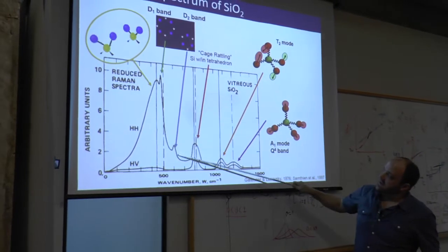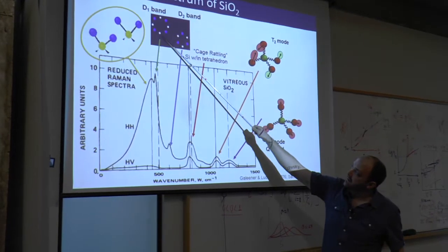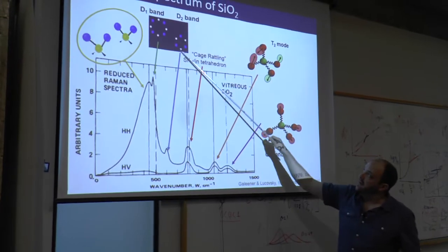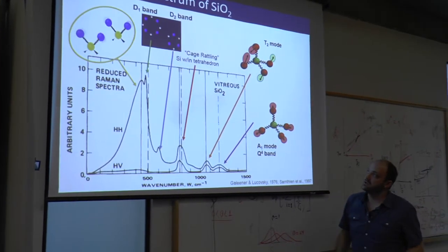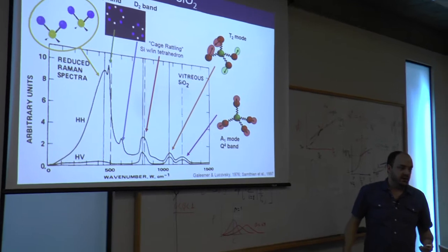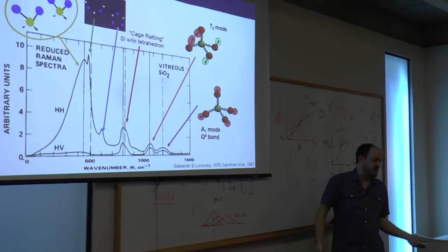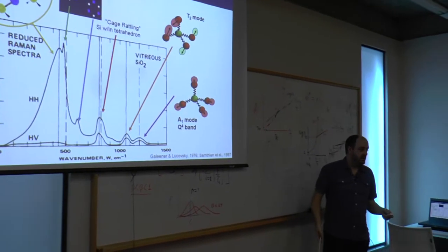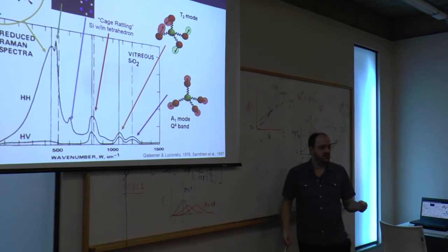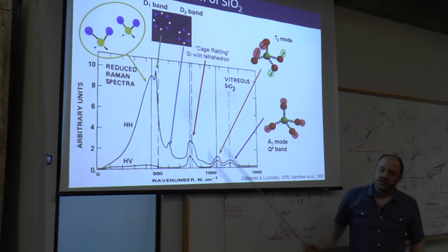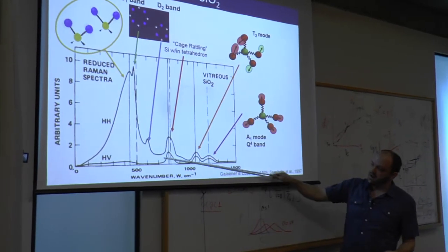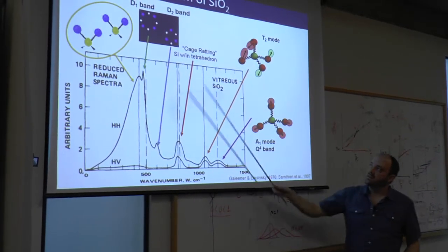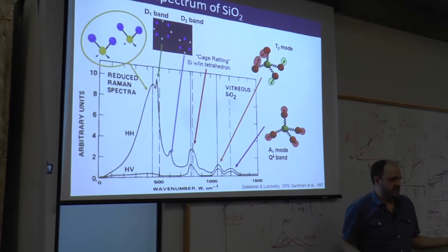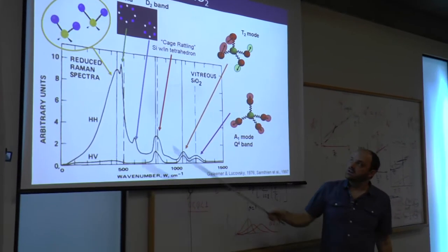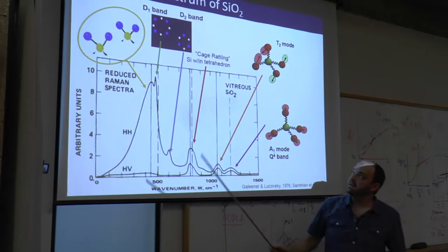There are these two bands here, and you can see that they belong to these 4-member and 3-member ring structures. They were identified very early on. Silica glass was first measured right after Raman made his discovery, I think in the late 20s or early 30s. And they thought that these sharp bands were too sharp. When we see the other bands in glass, they're quite broad. So they thought they were defects, that something else in the network was broken. So they called them the D1 and D2 bands.